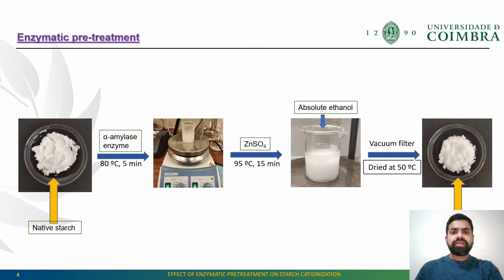printability. Further in enzymatic pretreatment, corn native starch was pretreated using alpha amylase enzyme and heated for 5 minutes at 80 degrees centigrade. Further, the temperature was raised to 95 degrees centigrade for 15 minutes for cooking the starch.